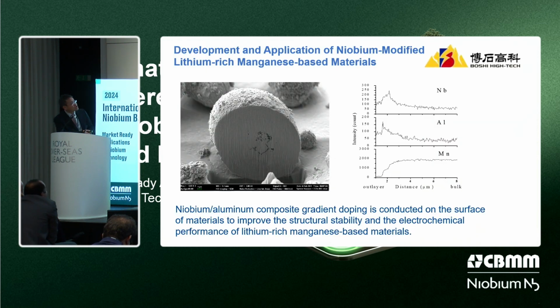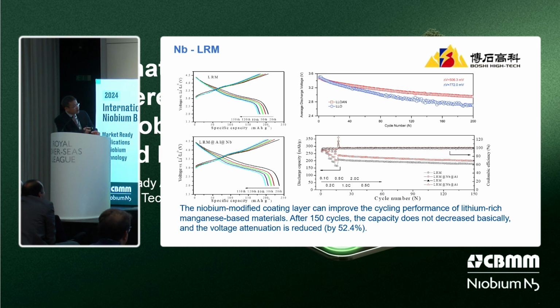And for Boshi, this is one case of modified LMR. They actually use niobium together with alumina. This is also very popular in China. Niobium plus alumina or niobium plus Mg, for example, in LMFP, and sometimes maybe titanium. Yeah. And they also found on the surface you could find this kind of niobium layer. And here shows some performance they developed. Okay, this is without niobium, and this is with niobium and aluminum, and also the discharge capacity.